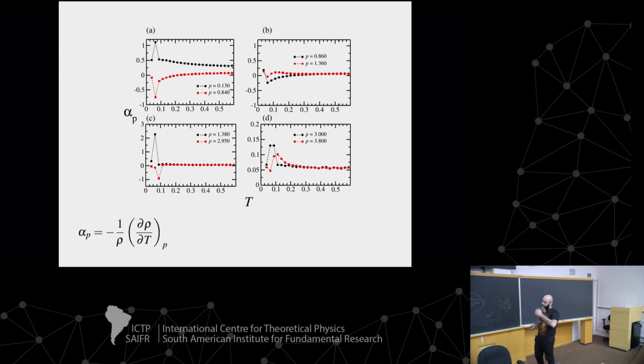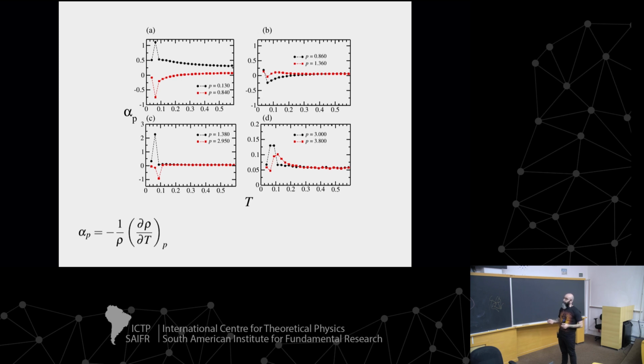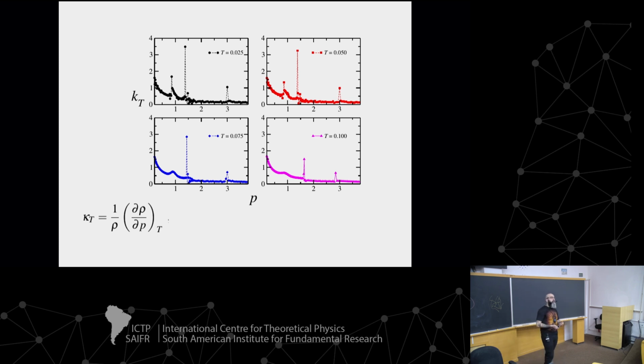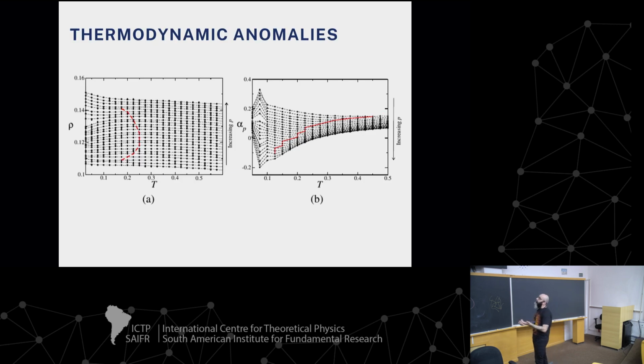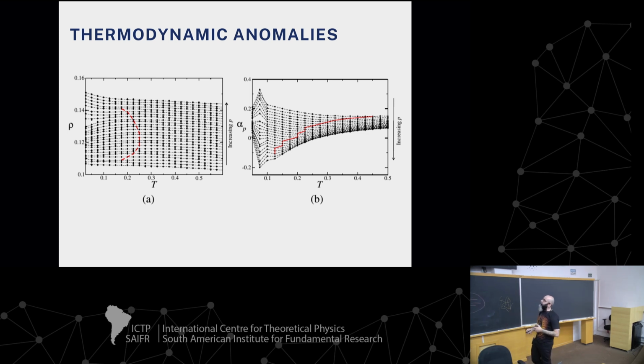We also evaluated other thermodynamic functions such as the isobaric thermal expansion coefficient, and the KT, the isothermal compressibility. And here also we found something really nice. At really low temperatures, remember, this is an effective model, all the units are reduced units. You can see that here, for the lower pressure or lower densities, you have a kind of discontinuity with this point going up, but here it is more like a bump, more like a maximum at slightly higher temperatures. Obviously, we will try to understand what happened. But we have the thermodynamic anomalies. Here is the TMD. We also get the minima in the alpha P.